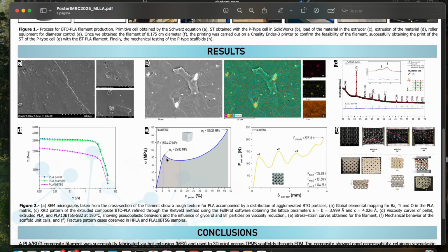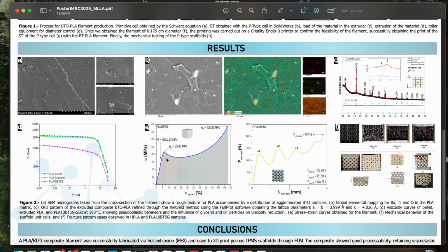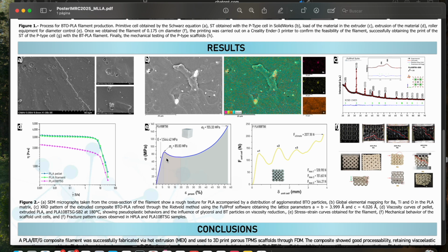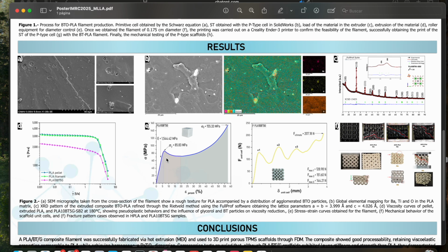The powder XRD pattern is well indexed to tetragonal BaTiO3 with refined lattice parameters a equals b equals 3.999 angstroms and c equals 4.026 angstroms, and a good fit quality, chi squared 1.08, confirming phase identity post-extrusion.